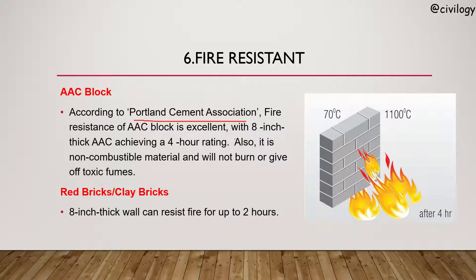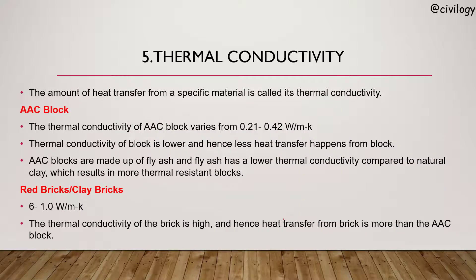Next, fire resistance. According to the Portland Cement Association, fire resistance of AAC blocks is excellent — an 8-inch AAC block achieves a 4-hour fire rating. It is also non-combustible and will not burn or give off toxic fumes. For red bricks or clay bricks, an 8-inch thick wall can resist fire for up to 2 hours. So AAC blocks are more fire resistant than clay bricks.